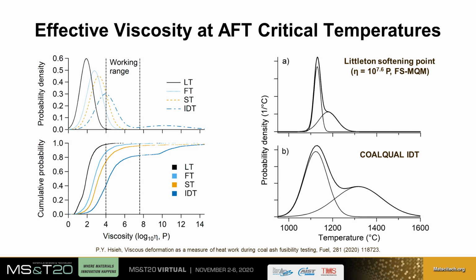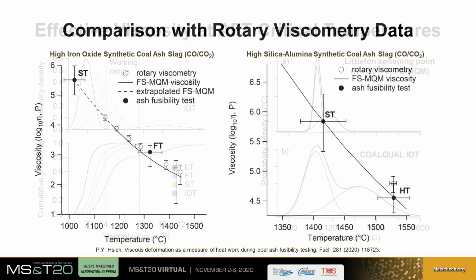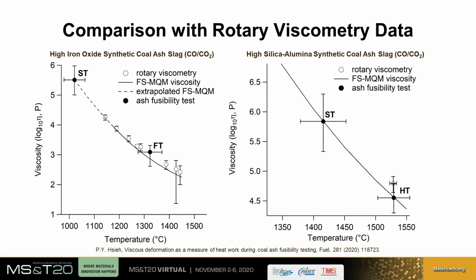Interestingly, the temperature distribution at the Lyttleton softening point correctly reproduces the bimodal distribution observed in the initial deformation temperature from the coal quality database. This is probably not a coincidence. But, to be sure, the modeling approach was checked in the lab through high-temperature rotary viscometry with two synthetic coal ash slags, a high iron slag and a high silica and alumina slag. The same slags were also subjected to AFT measurements.